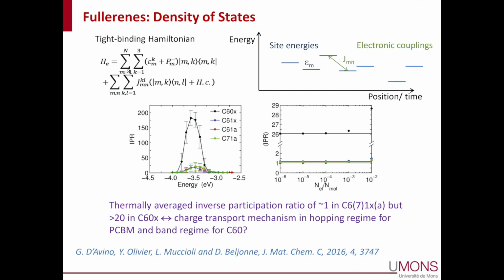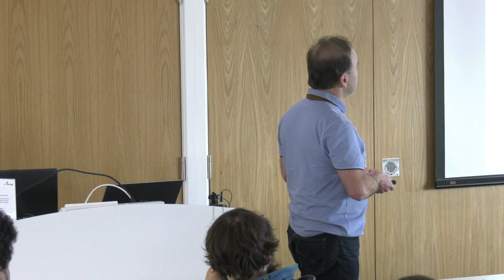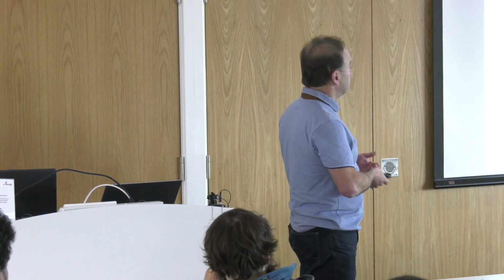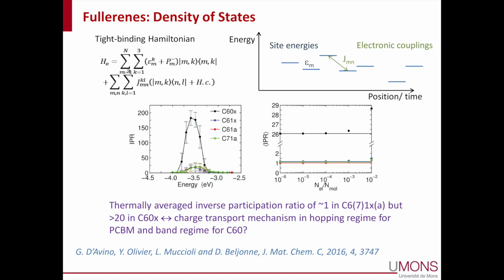To address that question, you need to set up this Hamiltonian with the variation of the site energy, the polarization effects and all the quantum mechanical interactions. So we can do that. I won't go into the details of how we did it, but you can solve the problem, and you can look at the inverse participation ratio, which is a measure of how much the charge is delocalized in those systems. And essentially the answer is, is the charge localized or delocalized? I mean, it's both. It depends really very much on the energy.